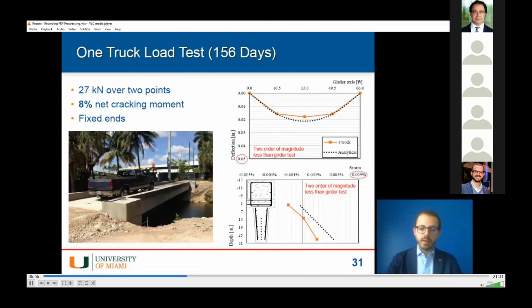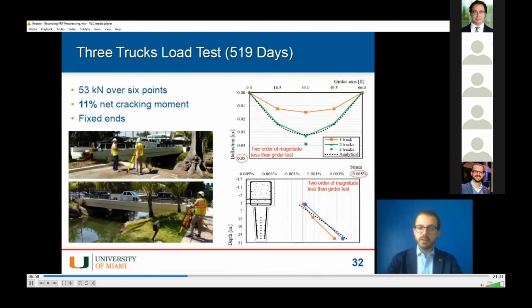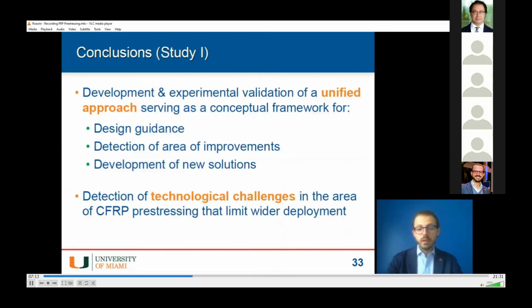And we went back again, this time with 3 trucks, and this time more than 1 year into the service cycle of the structure. Also in this case, you can see from the figures on the right that both in terms of deflections and in terms of strains, we have very good agreement with our theoretical expectation. This confirms our conceptual approach to design with FRP, be it pre-stressed or reinforced structures.